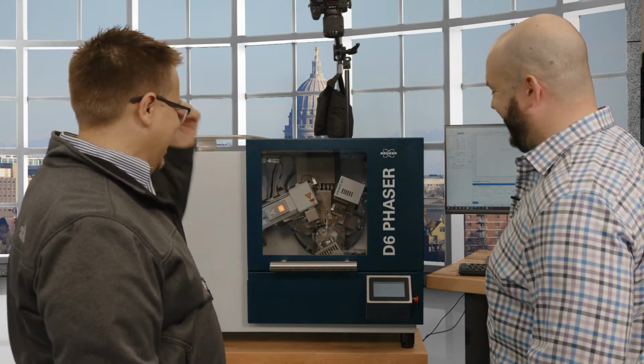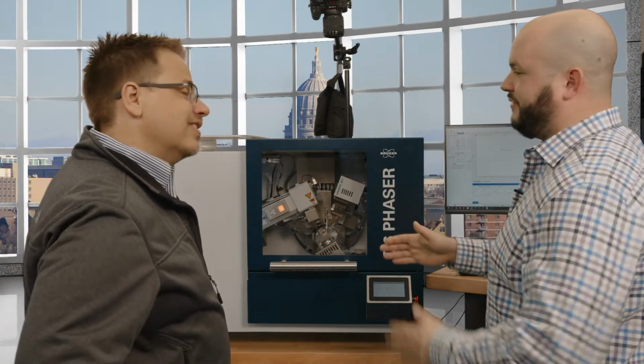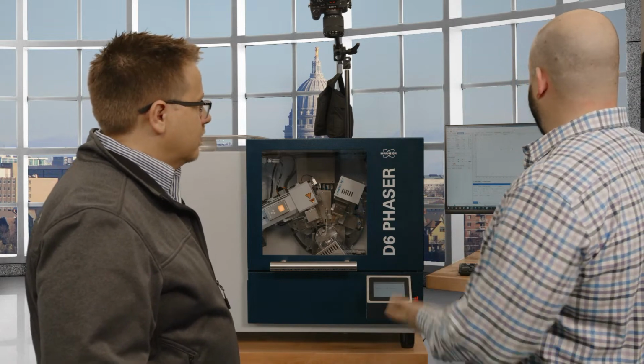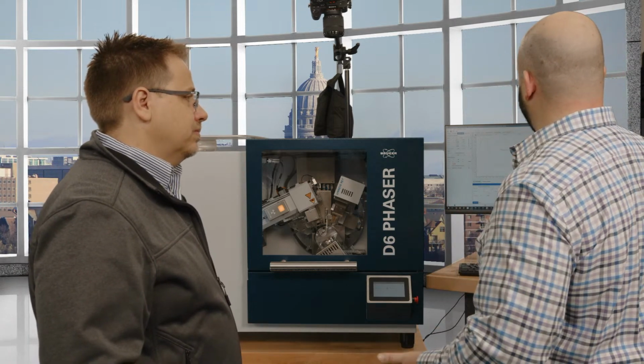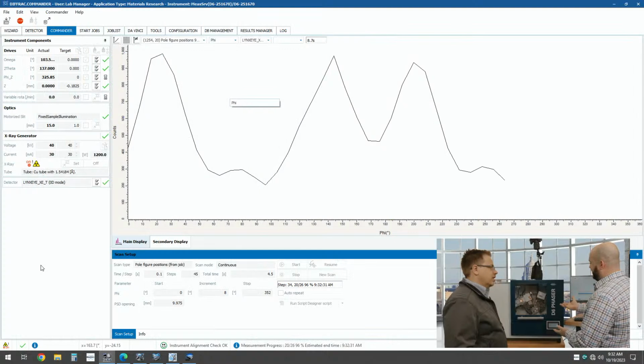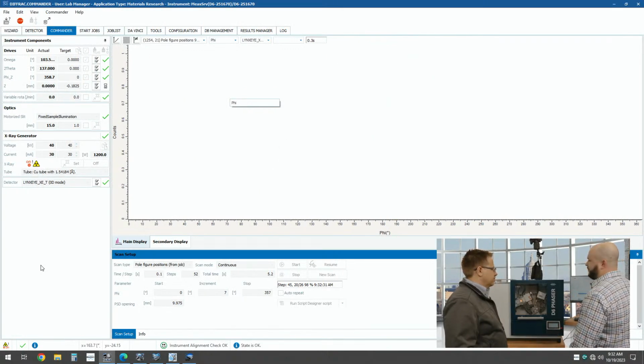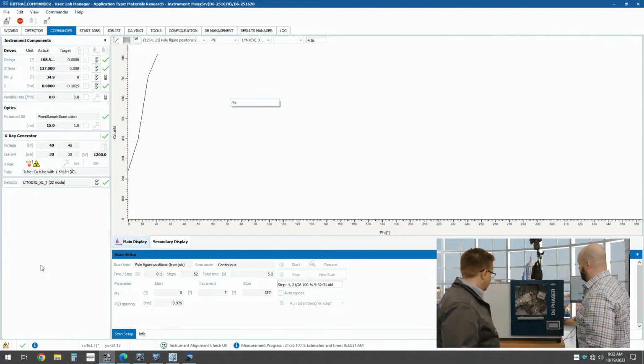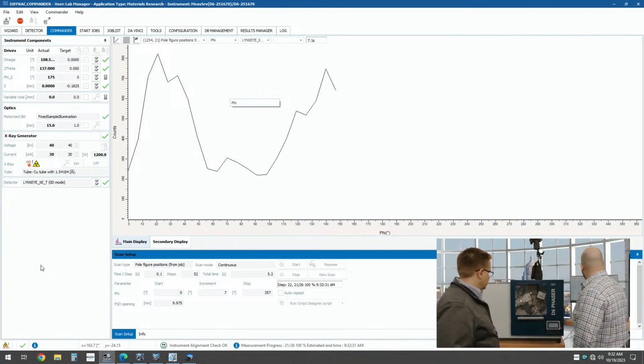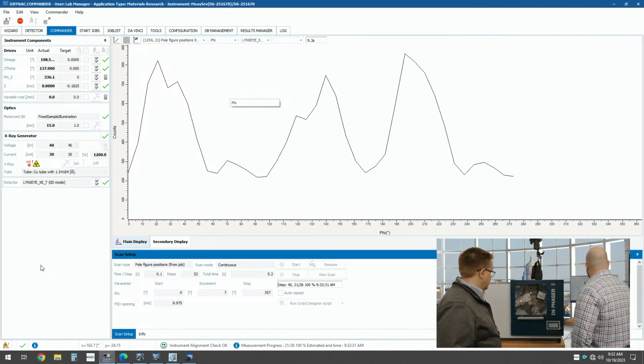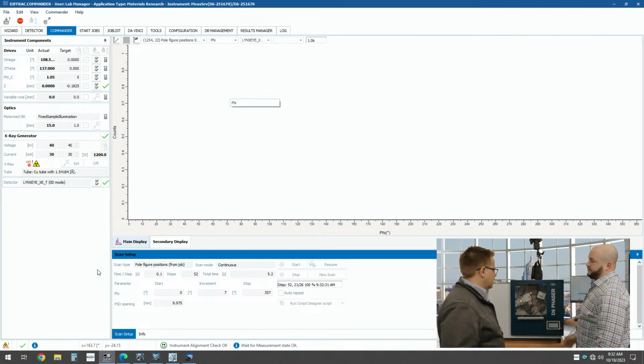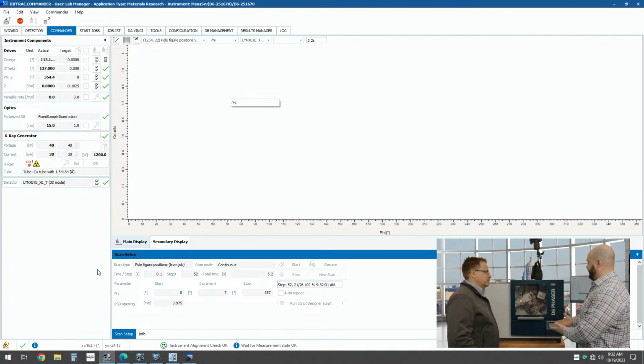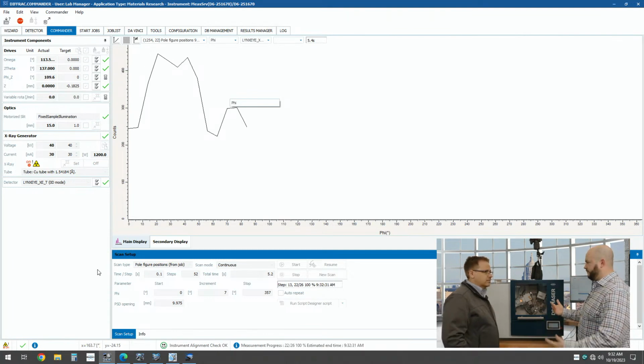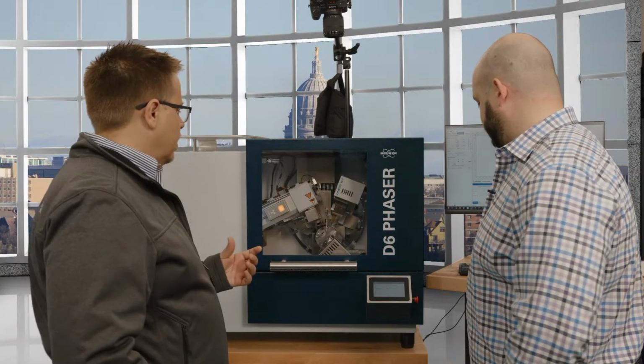What's really cool about this is I'm using fixed sample illumination. So we're getting reasonable peaks here, even though look at how fast it's spinning the sample, and we're getting reasonable information because we're illuminating the entire sample with X-rays, so we're getting a high flux. But that's texture in a nutshell on the D6. It's very easy to set up a measurement. Again, if you're doing multiple measurements, you can hit a button. All right, and then we'll have the next one now, which is the last one, residual stress.